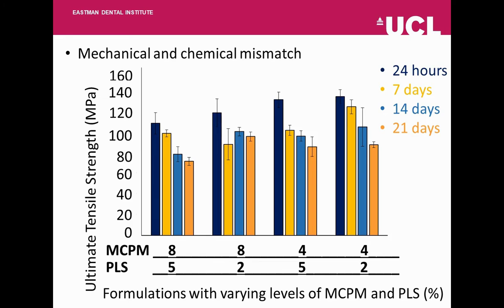So here is a graph showing the change in ultimate tensile strength over time in the different formulations with varying levels of monocalcium phosphate and polylysine. If we look at the x-axis, the first 2 groups consist of 8% monocalcium phosphate, and the second group consists of 4% monocalcium phosphate. Within the high and low levels of monocalcium phosphate group, we also have high and low levels of polylysine. The first group has the highest amount of monocalcium phosphate and polylysine, and the last 2 groups have the lowest amount of monocalcium phosphate and polylysine combined.